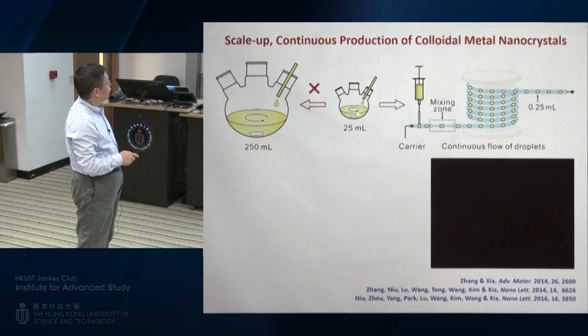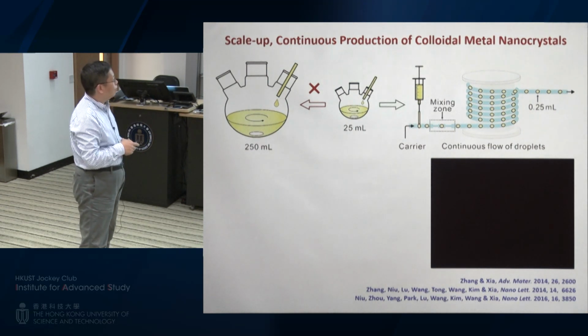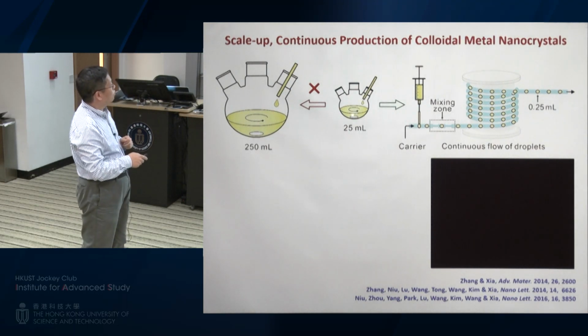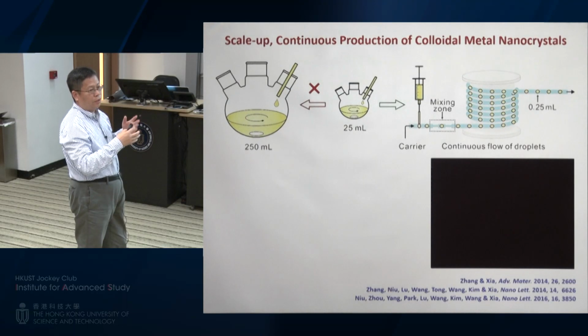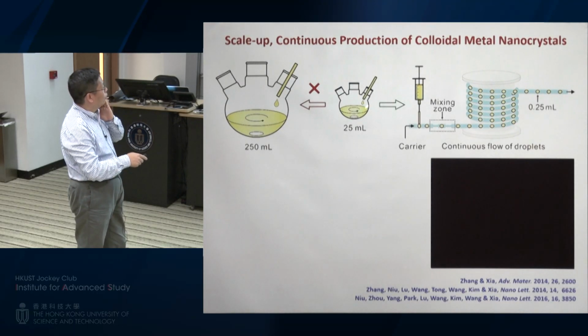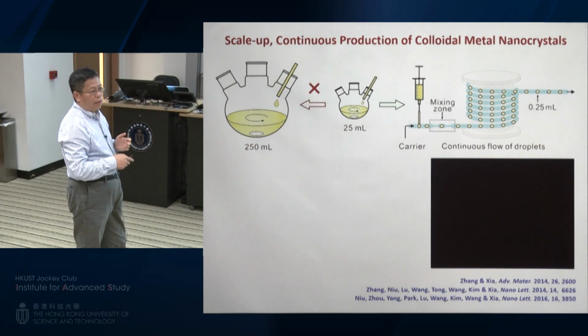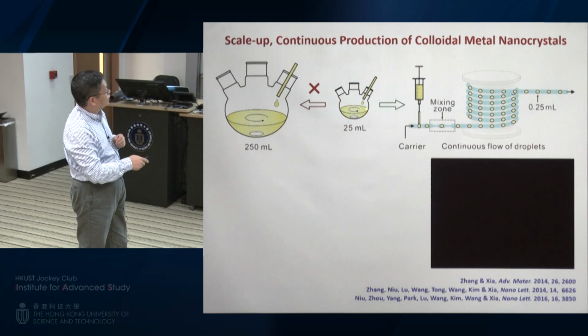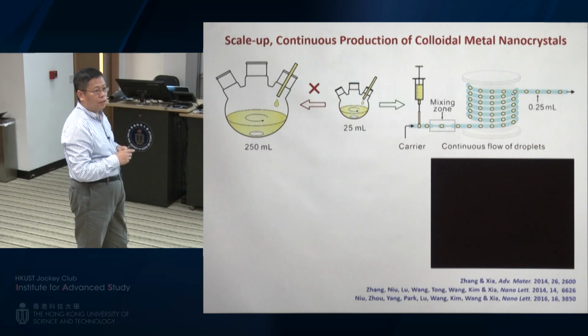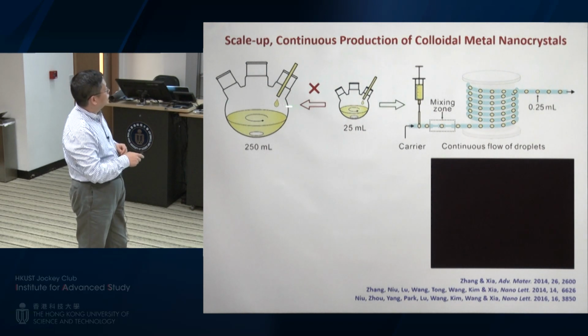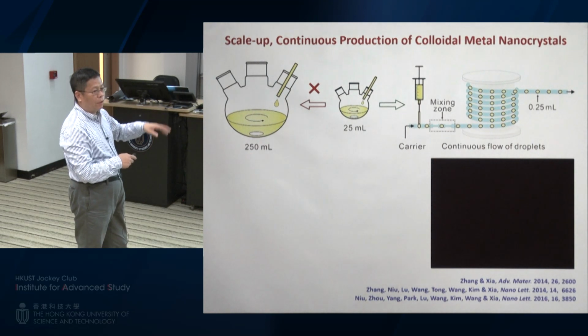And for scaling up, people used to think in this way: just use a larger container, use more reagents, and of course you're going to have more products. But unfortunately, it turned out to be not so easy, because nanocrystal synthesis always involves heat generation, heat dissipation, and so on and so forth. Heat generation is volume related, but heat dissipation is surface related. So it's never going to be a simple scaling factor. You won't be able to succeed if you go this way. Your particles will definitely become less uniform and poorly defined if you go to a higher volume.